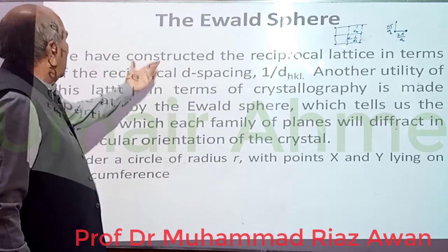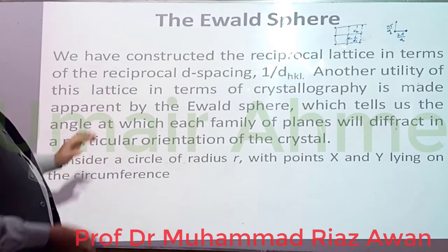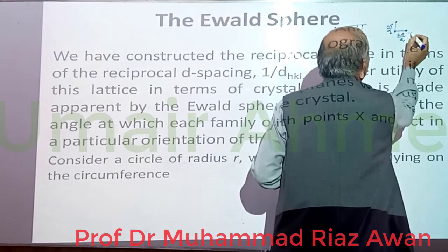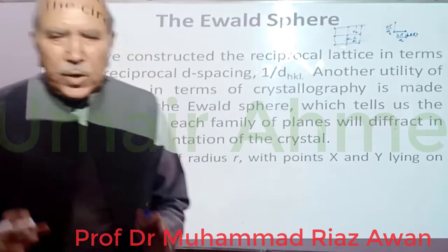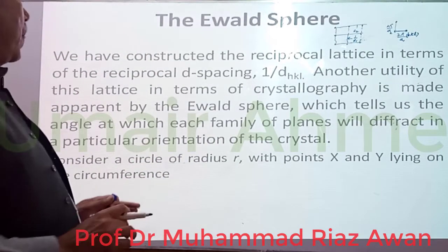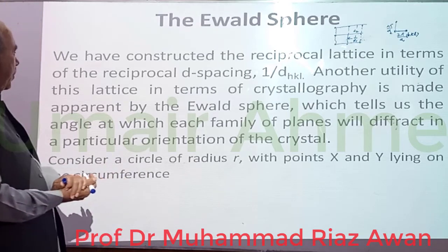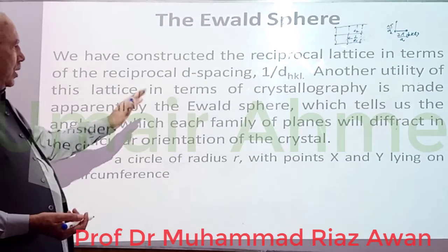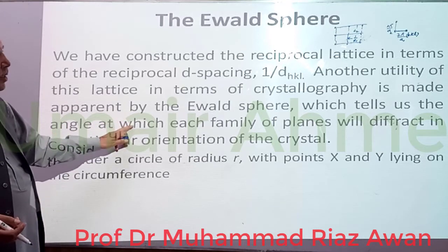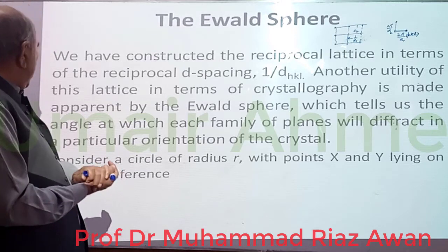So, what we do: we have constructed the reciprocal lattice in terms of the reciprocal d spacing, 1 divided by d hkl. This is the reciprocal lattice. This point represents a particular hkl plane, and this distance is the distance between the different planes, that is, the interplanar distance. Another utility of this lattice in terms of crystallography is made apparent by the Ewald sphere which we will construct today, which tells us the angle at which each family of planes will diffract in a particular